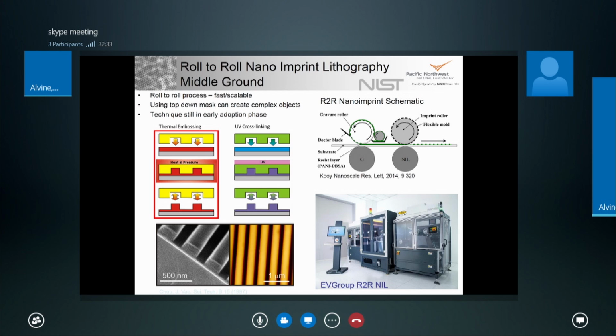I'd be remiss if I didn't mention a middle ground, and that's nanoimprint lithography. You take a hard master or mold created typically by E-beam or photolithography, and you can make whatever nanostructure you want. That's going to be very expensive, but then you can replicate it in a soft material like a polymer over very large areas in a roll-to-roll process. So this potentially allows you to strike a middle ground between complexity, cost, and scale-up.